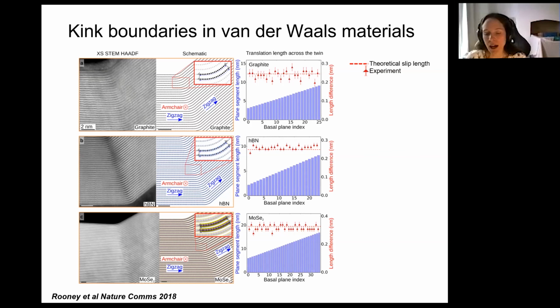So if you're taking one sheet of graphite and you're slipping it over the next, it doesn't want to slip by any arbitrary value. It wants to slip by a known distance, which translates your AB stacking to BA stacking, for example, or to ABC stacking. Okay.